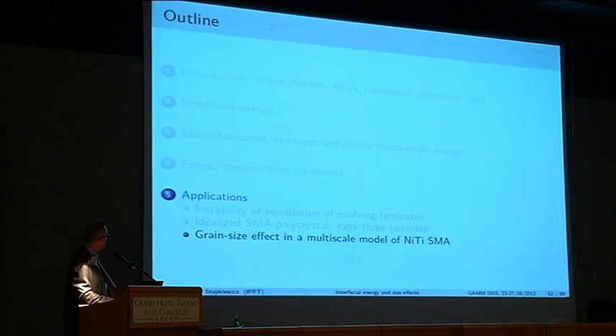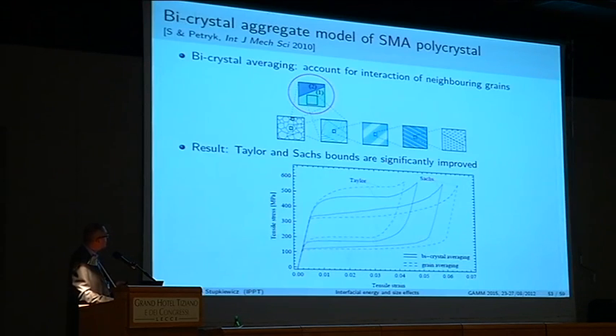So this is the first and final example where we have included the interfacial energy into a more general model for an SMA polycrystal. As a starting point, we take the model that we have developed, which we call a bicrystal aggregate model. In this model, we assume that the material is not an aggregate of grains, but an aggregate of bicrystals. Each bicrystal is a grain boundary with the adjacent parts of the two grains. In that way, we can account for the interaction of neighboring grains. The result is that, for instance, the simple Taylor and Sachs bounds are significantly improved. I won't elaborate more.